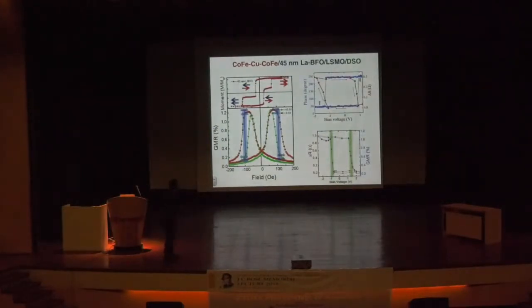So basically, you could see we have now built spin valves on a 45 nanometer multiferroic. That's the nice GMR hysteresis loop. This is exactly what it should look like, textbook almost. That's basically the GMR resistance versus magnetic field.